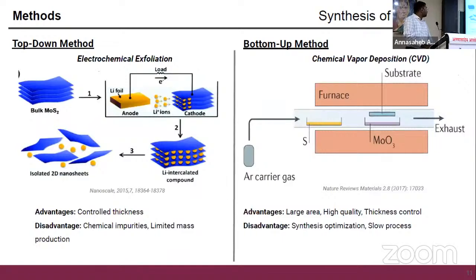People also use other techniques such as electrochemical exfoliation, as you may have learned about in your coursework. Basically, by intercalation of lithium ion into the layered structures of these materials, you can separate them from each other, and then by using some ultrasonic energy, we can keep them in separate stages, as well as isolate them using some organic ligands.